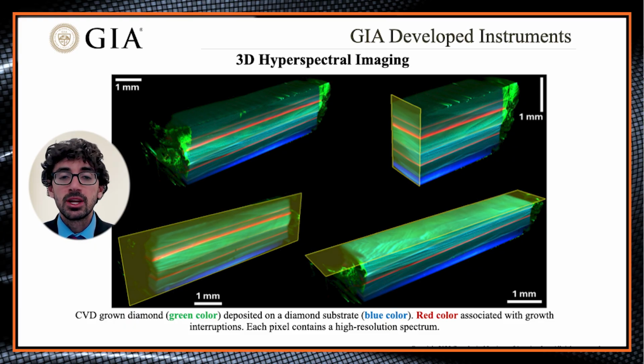In the following image, this is an example dataset for the three-dimensional hyperspectral imaging system that we have developed at GIA. What you are seeing here is four cross-sections showing the total stone, and then different cross-sections following either the XY, XZ, or YZ planes. This shows us the evolution of this CVD diamond as it grew, which is very difficult to see with other techniques.